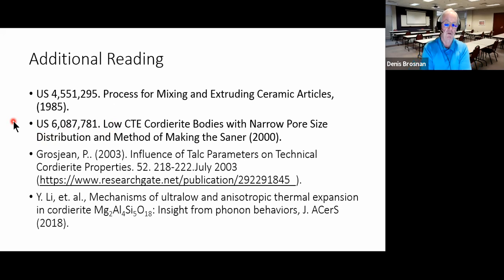Now, when cordierite first came out as a catalyst support, the catalyst support was fired, and then you put a wash coat of porous alumina on the surface to accept the catalyst. And that was fired on. My impression is that cordierite may have evolved in production to where you eliminate that second handling operation and can make a porous enough ceramic to accept the catalyst and to accomplish any filtration that you want without having to go through a two-step process.